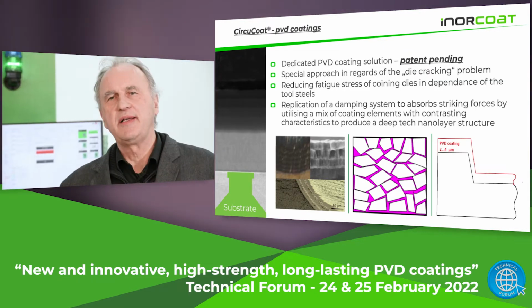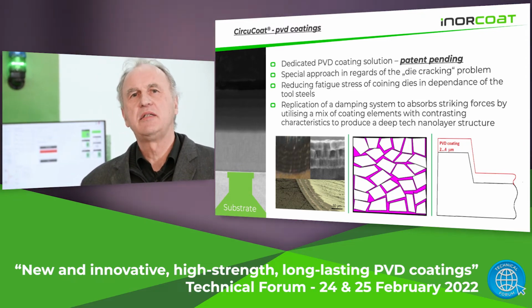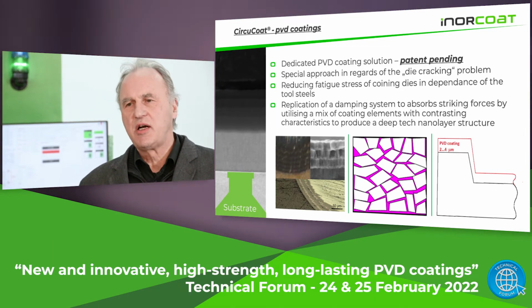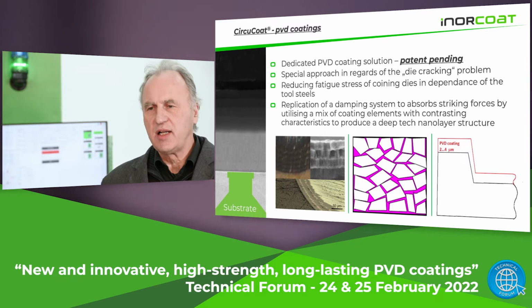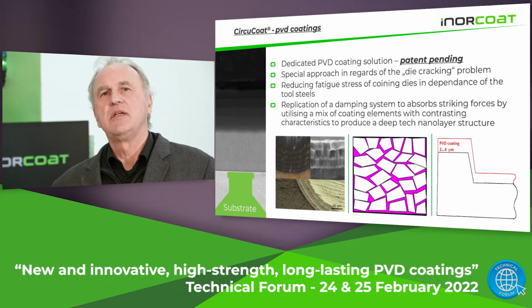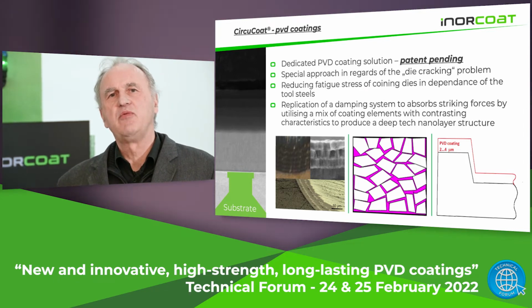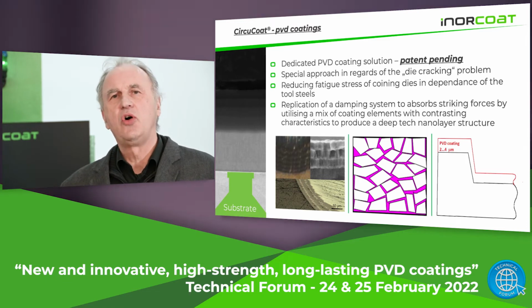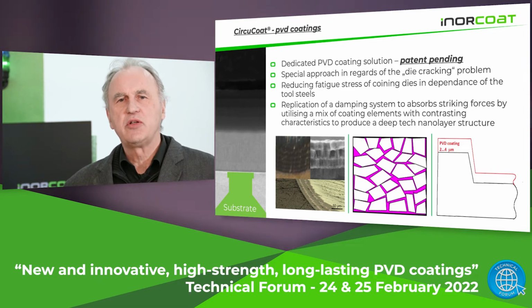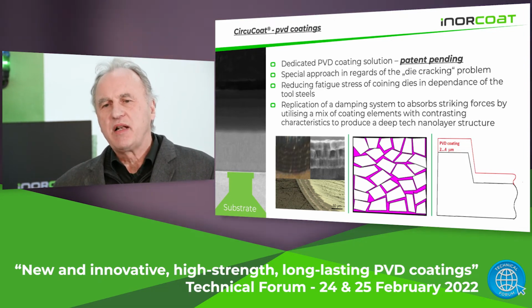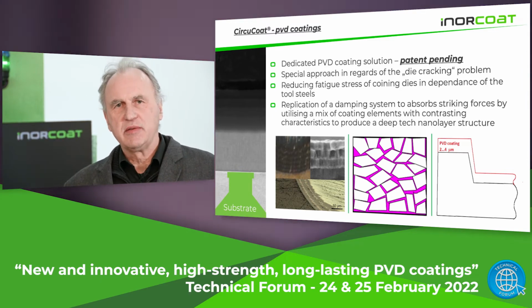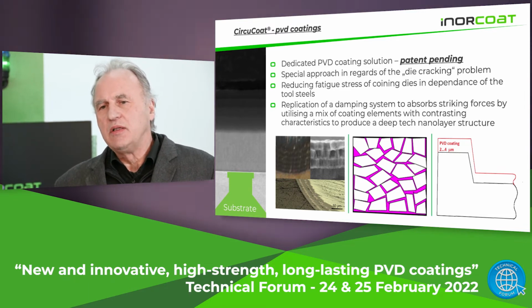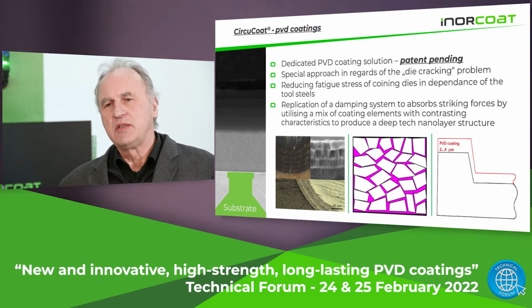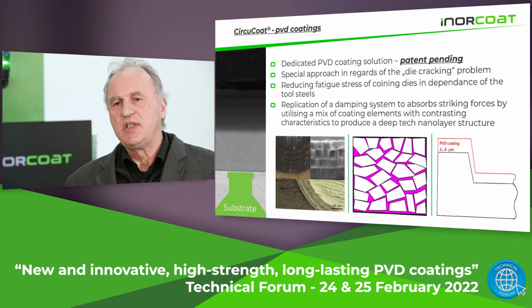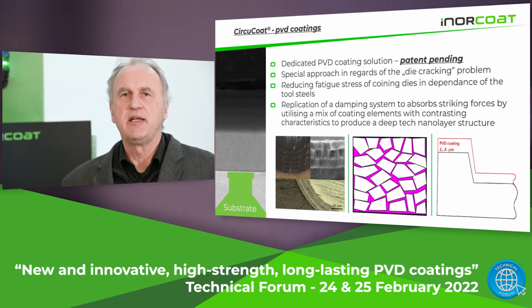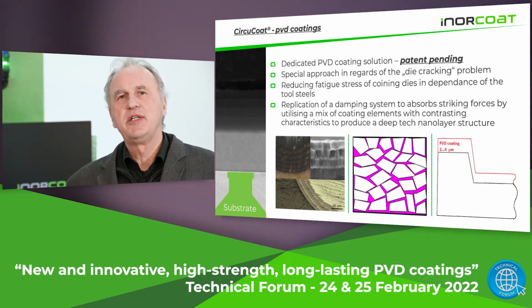The basis of the PVD coatings are ceramics. Ceramics are hard, ceramics are brittle. So the hardness of the ceramics is typically 4 times the hardness of hardened steel. What we do is we introduce into these hard ceramics soft metal phases. We introduce them in the form of nanocrystals or in the form of nanolayers into the ceramic coating. And these soft metal phases stop the cracks immediately after starting. And this turns the whole coating very tough. And they not only stop the cracks when they start, they also provide that the cracks do not propagate until the substrate and propagate into the substrate, and therefore the coating also protects the substrate.